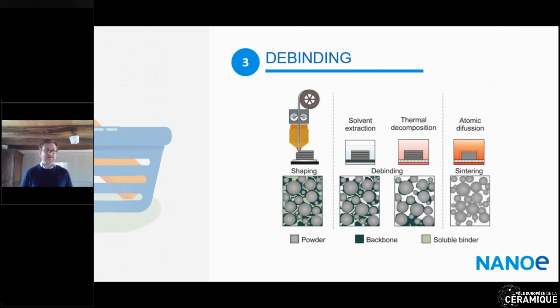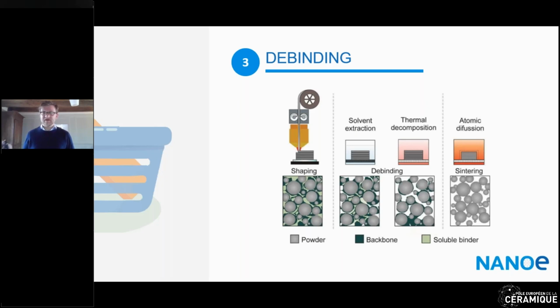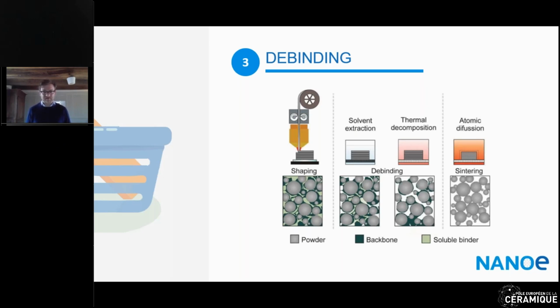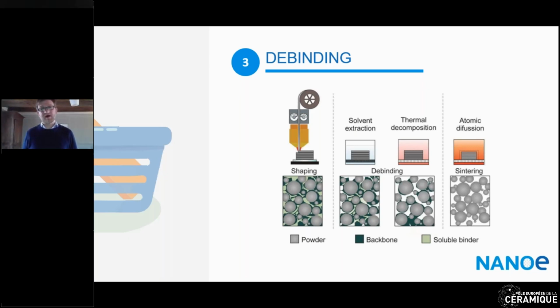Once we have printed, we get to the, I'd say, most complicated phase, which is debinding and sintering. The objective of debinding is to remove all the plastic binders without damaging the part, and that's really a critical thing. Managing to remove all of the binder without having any cracks, any damage, any deformation in the part. This is usually done by a two-step debinding process. The first step is solvent extraction. We will dip the part in the solvent, in our case it's acetone, and then the thermal debinding, we put the part in the furnace, and in the furnace we will burn the rest of the binder.